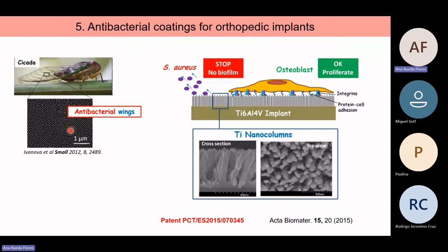Bacteria cannot proliferate on this surface. The pillars are made of chitin and lipids, but what is really important is the morphology. So our idea was to coat orthopedic implants with titanium nanocolumns, and the idea is that the bacteria cannot attach, whereas the cells that are much bigger can proliferate.